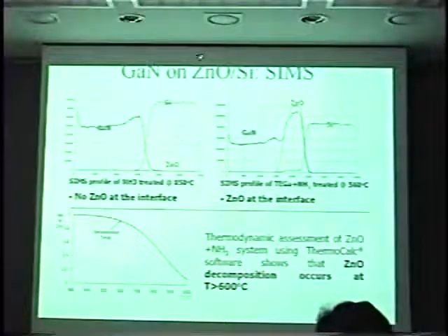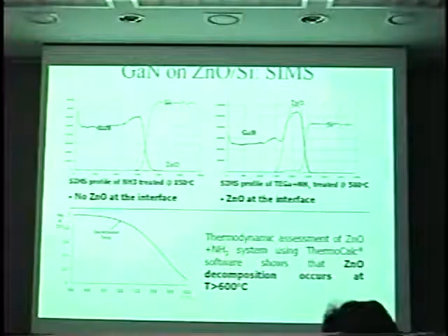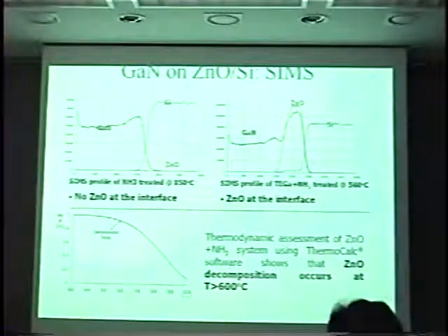Another approach was to use zinc oxide. Zinc oxide is fairly closely lattice matched to gallium nitride. The problem with zinc oxide, though, is it's fairly unstable. Thermodynamic analysis indicates that above about 600 degrees centigrade, the zinc oxide will blow off, will thermally decompose, and we really won't have the buffer layer to grow upon. So here are some preliminary experiments we did with ammonia treatment. At 850 C, we see no evidence of zinc oxide. The zinc oxide just dissolved into the gallium nitride and underlying silicon. But if we keep the temperature below about 600 degrees C, we can retain the zinc oxide at the interface.